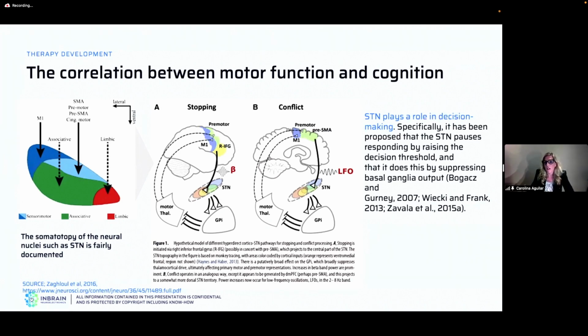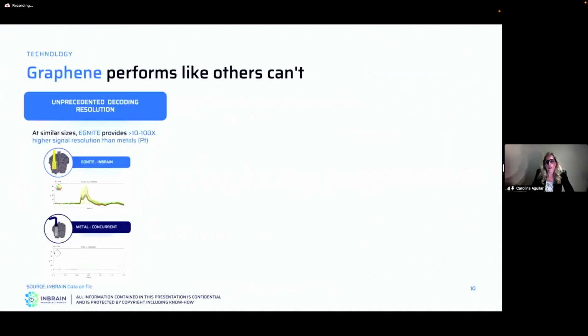In the case of conflict, there's a very similar path. These pathways are regulated by brain signals. In this case, beta correlates more to the stopping, and low frequency oscillations to the conflict. What we are doing here is studying these correlations at a very high resolution and with a lot more information than before. As an example of what we've achieved in the last years, looking at the resolution from graphene to metals, we see, as we said before, 10 to 100 times higher signal resolution than metals. We're looking with both metals and graphene.